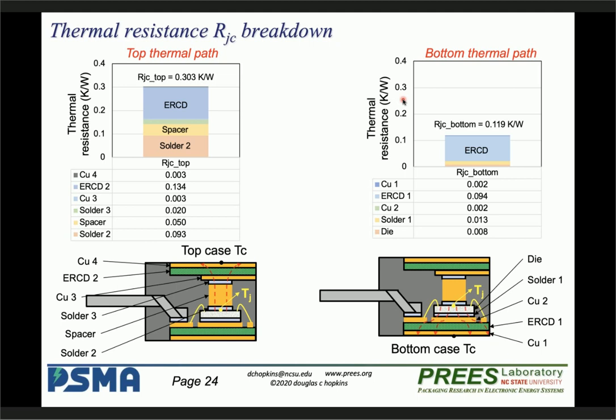It is because the area of the spacer is only 60% of the device. So less area will lead to the higher thermal resistance. So that's why the bottom RJC is lower than the top one. And by paralleling top and bottom RJC, we can get the total, or we call the equivalent RJC here. So it's around